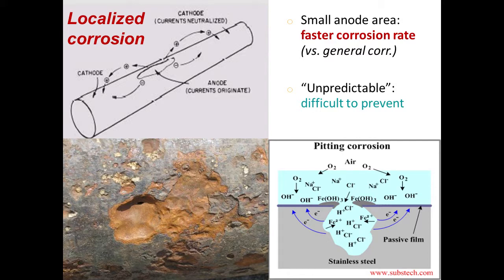Now again, localized corrosion is very dangerous, as we already mentioned, because remember the two half reactions. One is trying to oxidize, creating a lot of electrons, and those electrons need to be consumed by somebody else. So when you have localized corrosion, for instance, one example is you have a coating which is dented, you have a hole. That hole becomes the so-called local anode. It's trying to produce a lot of electrons to protect adjacent areas because it's a marriage. Now, this is not an equal marriage. So all of a sudden, that hole is corroding 10 times faster than the uniform corrosion rate.